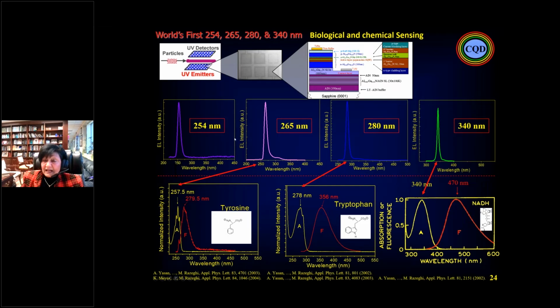That was the thing that we did. The world first 308, 340 nanometer, 280 nanometer, 256, 254, and at exactly that equivalent we did the detector. And for all of that, as you can see, for the different agents, and especially for the anthrax at 280 nanometer, it was very important, and DARPA immediately put out the BAA, and it was a very hot subject, and we demonstrated one after another.